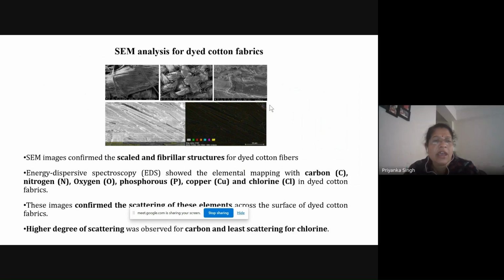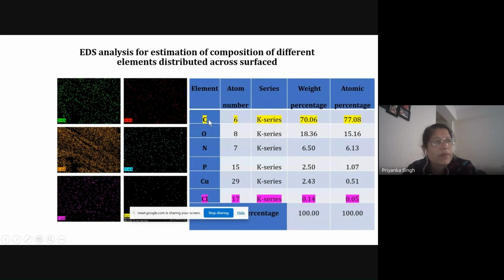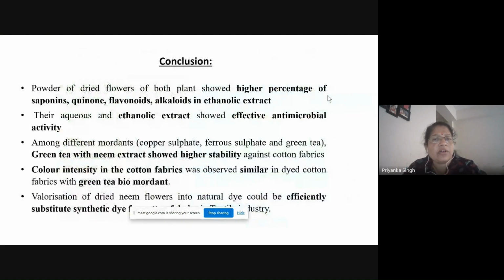Then we have performed the same analysis, which confirms the scaled and fibril structure across it, and this shows the presence of carbon, that is the scattering of the carbon. We obtained a major percentage for carbon and a minimum for chlorine. So this is all about my study, and finally I would like to conclude that this natural dye based on green tea can be used as a low cost, effective natural dye for commercial purposes in the textile industry. So this is all about my work.